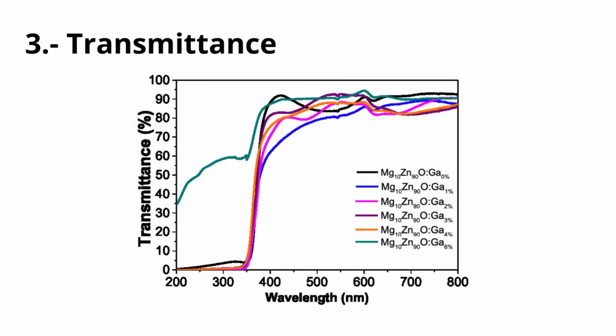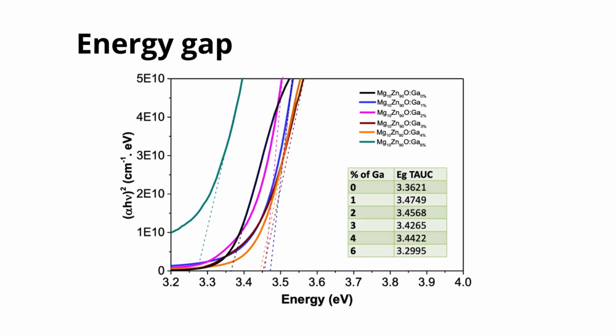The third step is transmittance. In this case, we use a Cary 5000 UV-Vis-NIR spectrophotometer with a deuterium arc UV light source and a tungsten halogen visible lamp to monitor the transmittance spectra of the films in the wavelength range of 200 to 800 nanometers, which were analyzed using Cary WinUV software. As can be seen in the figure, the samples have a transmittance greater than 80%, which is very good for applications.